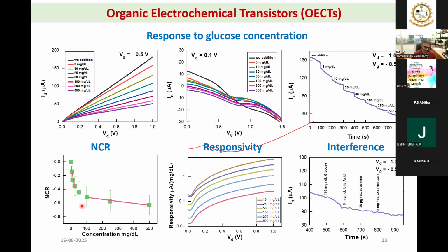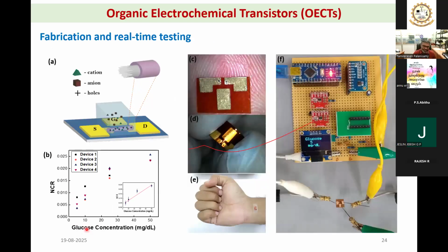This tells us that the sensor is working very precisely, or the responsivity is much better at a lower concentration. So that is why we did not use it for blood level of glucose, because the blood level of glucose will change typically from 50 milligram per deciliter to all the way to 500 or even higher. Anything less than 70 is called hypoglycemic, and more than 120 is called hyperglycemic.